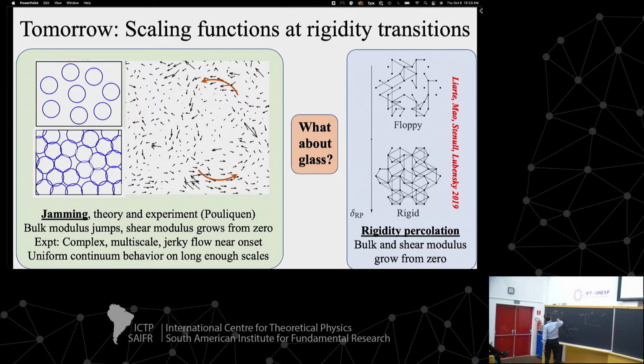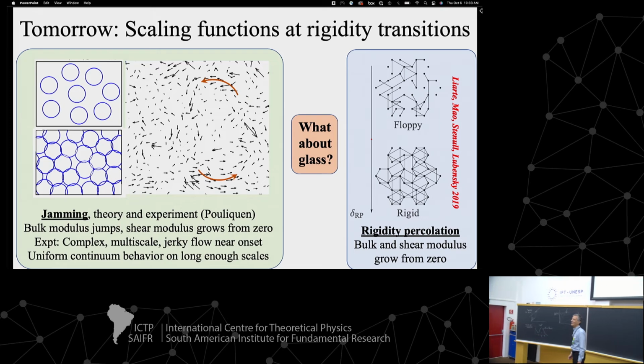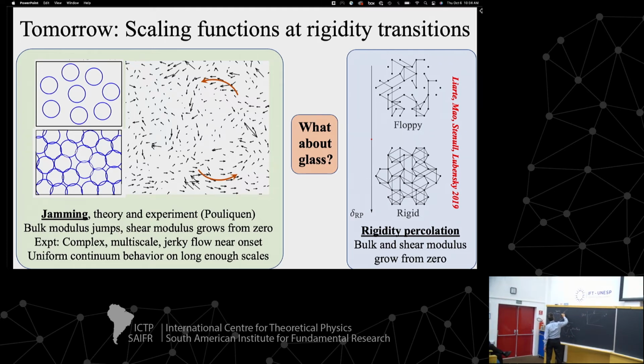Then when you increase T, you need to move away from the jamming line. But really close to jamming, in a region that scales with h bar, you can get T. But this would be a different T. When you go away from jamming, the low frequency part will become T cubed. Exactly. So that's not the same as the real glasses, where this is quantum tunneling.